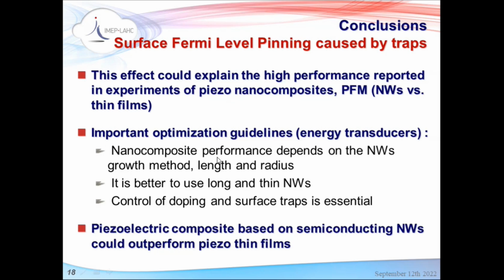For instance, the nanocomposite performance depends on the growth method of the nanowires, and in general on the length and the radius. I didn't show you results on the length, but you can believe me, length is also important, and it is better to use long and thin nanowires in general. And it is important also to control the doping and the surface traps in the future. And then overall, piezoelectric composites based on nanowires could outperform piezoelectric thin films.